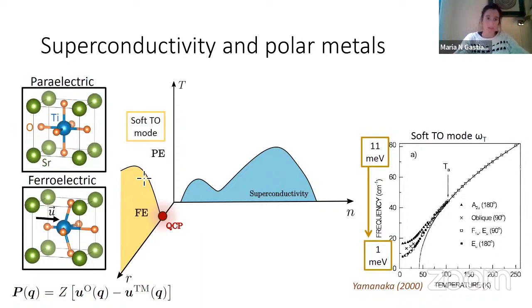And often this kind of transition can be described by, or is accompanied by, the softening of a transverse optical mode. Here I'm showing the softening from hyper-Raman data of strontium titanate. So you see, as you follow the frequency of this transverse optical mode, the bare frequency gets extremely soft, and eventually, even though it should cross zero and go into the ferroelectric phase, it gets this kind of curvature. It has been said that this is because it's a quantum paraelectric, and this never goes into the ordered phase. It's a prototype of an incipient ferroelectric.